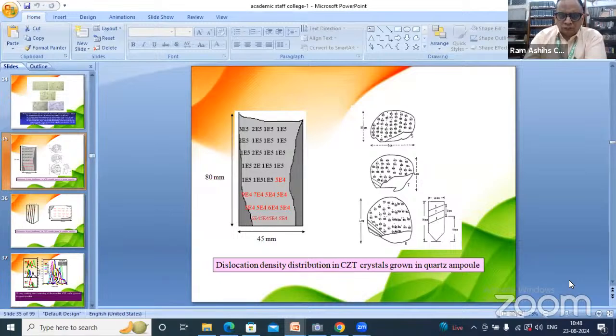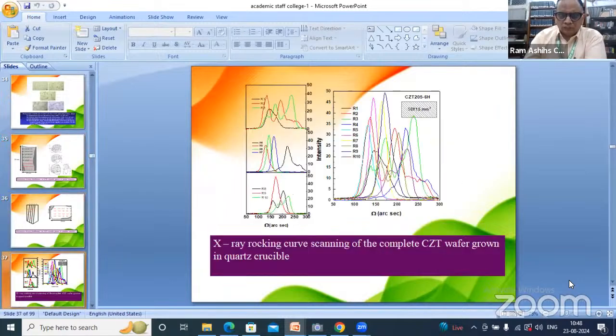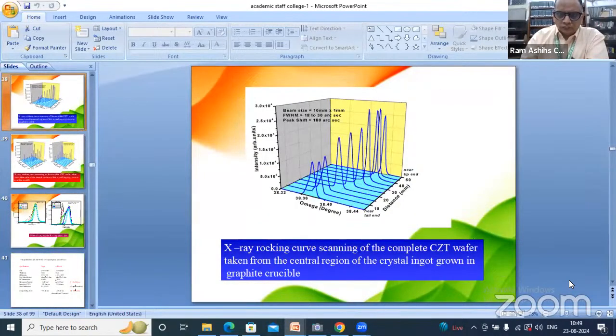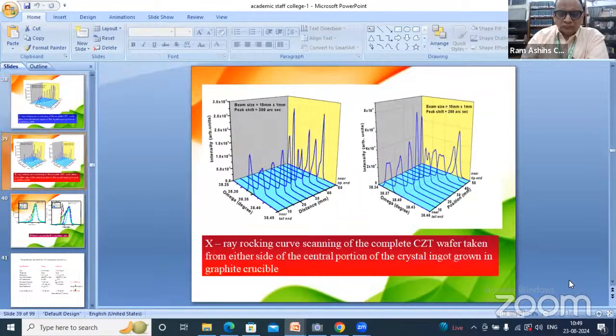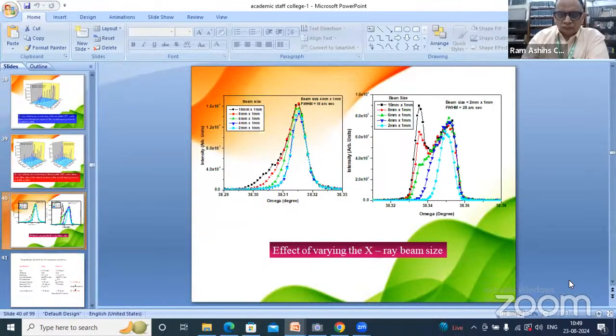This is the EPD mapping. This is the X-ray rocking curve. The splitting of the X-ray rocking curves has the physical significance that low angle grain boundaries are present in the substrate in one region. This is the perfect single crystalline quality. This is a different beam size, and the splitting, with multiple peaks, shows the tilted low angle grain boundaries present in the substrate. These are also analysis.